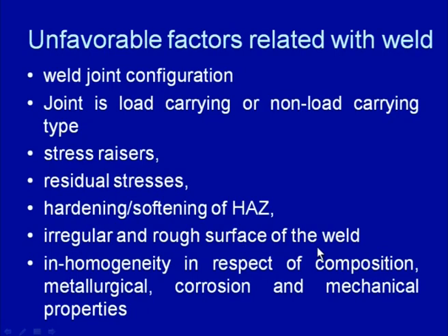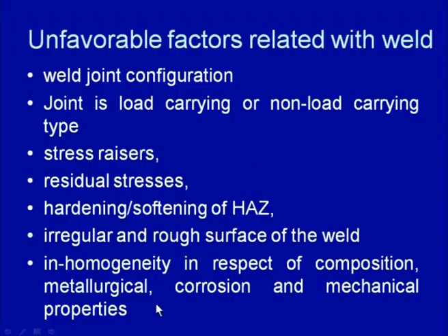Similarly, irregular and rough surfaces will facilitate crack growth in the initial stage, and thus they will adversely affect the fatigue life. And inhomogeneity, which is invariably present in the weld joint in respect of composition, metallurgical characteristics, corrosion and mechanical behavior, further facilitates the nucleation stage and the crack growth stage, and thereby adversely affects the fatigue performance.